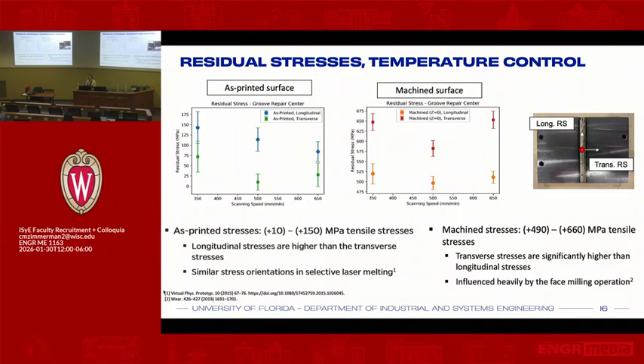So by understanding both of those sets of parameters that we get in this particular repair, we now could, for example, if you see that you're doing a printed surface that is going to provide you a tensile residual stress of positive 150 megapascal, for example, you can actually know that you can change the power input. And that power input would actually then reduce that tensile stress. So that will be part of what will go into your closed loop mechanism.